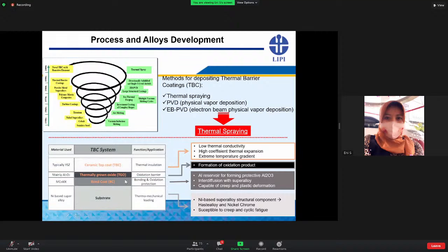This figure shows the schematic illustration of the thermal barrier coating system. There are three primary coating layers in the TBC system, as shown in this video. M can be composed of nickel and cobalt, and X can be added as the reactive element. It's a bond coat layer, approximately 200 micrometers thick, which provides bonding and oxidation protection, mainly an alumina layer. The second layer is the thermally grown oxide, which grows from 0 to 10 micrometers and acts as a diffusion barrier. Typically, yttria-stabilized zirconia is the third layer, the ceramic top coat in the TBC system, around 300 micrometers to 1 millimeter in thickness, which acts as the main thermal insulation layer.